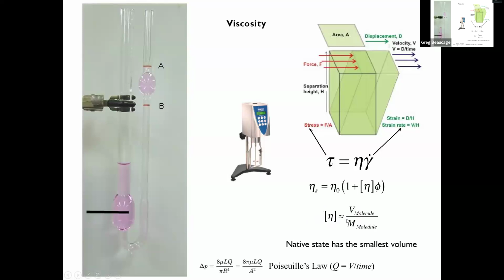And then that thing's going to depend on the molecular weight. Right, because the volume's going to depend on molecular weight, depending on what it is. So it'll be like R cubed, and R is going to be N^(1/2) times L, so R cubed goes as N^(3/2), and dividing by the mass N gives you N to the 1/2 power if it's a Gaussian chain. And then you can do that for the other expanded coils, rods, whatever you want.